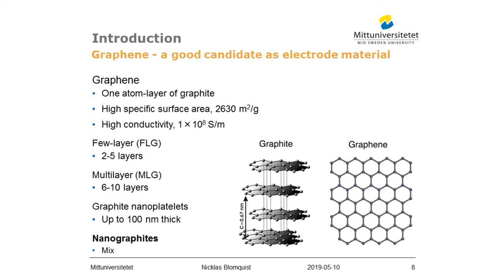Graphene is, in theory, a very good candidate as an electrode material. Graphene is defined as one atom layer of graphite, and it has a really high specific surface area. The surface area is more than 2,600 square meters per gram. So graphene is very, very thin. As a comparison, you only need 2 grams of graphene to cover a whole football field.